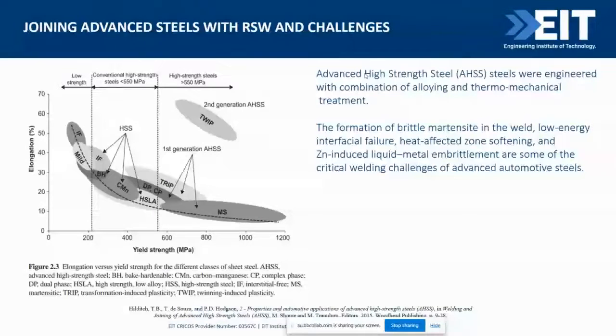All right, but going back to what I was discussing a while ago, with advanced high-strength steel, because of their natural ability to form martensite, this material will always break via interfacial failure. On top of that, most steels nowadays are coated with zinc in order to prevent corrosion. When this zinc melts due to high heat, it starts penetrating through the grain boundaries, and this gives another situation called zinc-induced liquid metal embrittlement. The whole weld can crack easily. That is a scenario we are looking into at the moment with these advanced high strength steels.